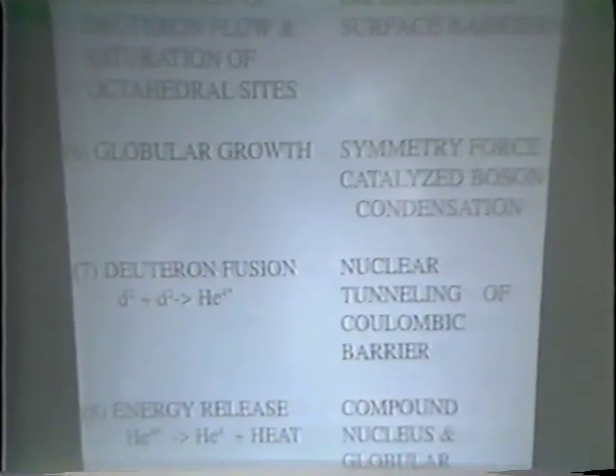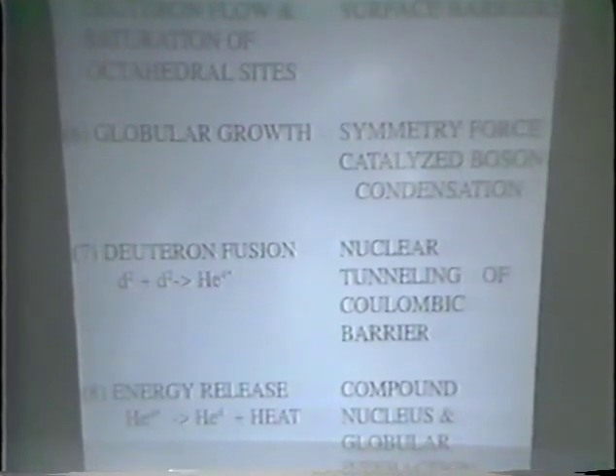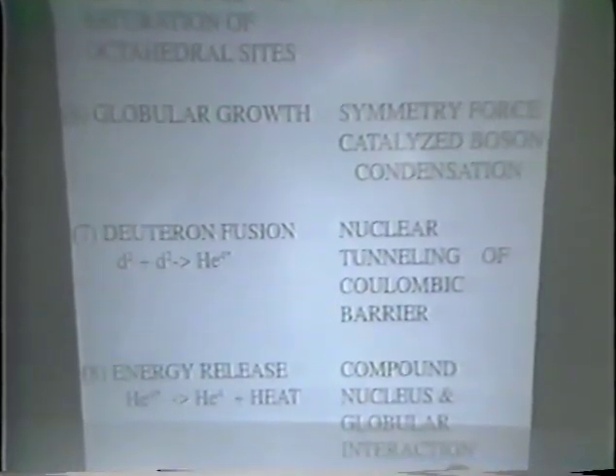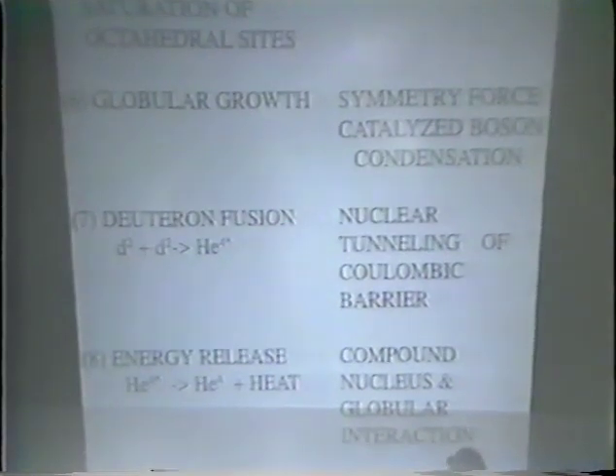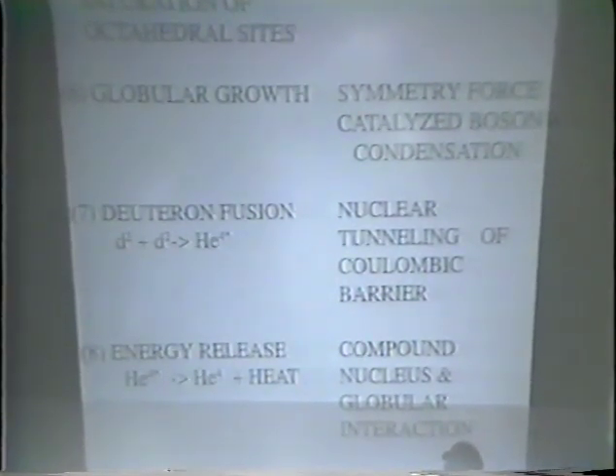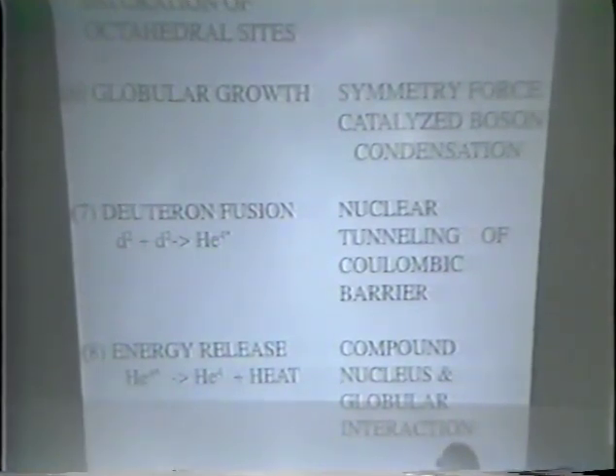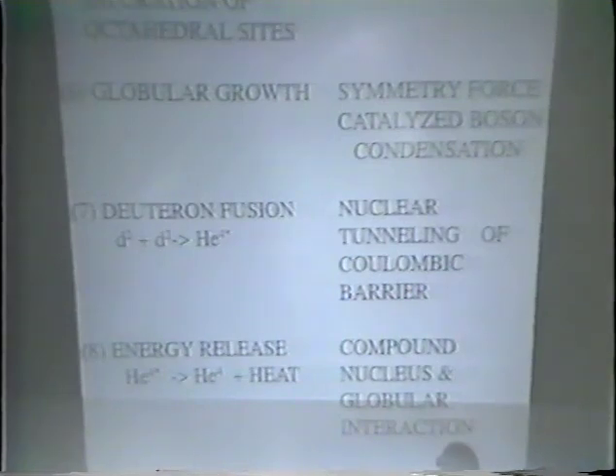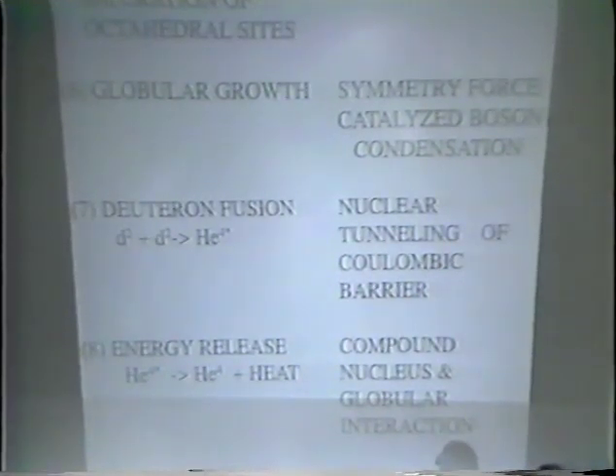Okay, once you've got the termination of the flow of these deuterons into the interior of the lattice, you've essentially saturated the octahedral sites. At this point, we believe that the globular growth will take over. The process Dr. Bush talked about, the symmetry force, due to the nature of the bosons, that they can start aggregating, and the more deuterons you get in an octahedral site, the greater the tendency to pull in others. And now, once you get enough in there, the separation distance is going to be sufficiently small that the probability of nuclear tunneling taking place is going to be relatively large, and that's going to be the seventh step here.